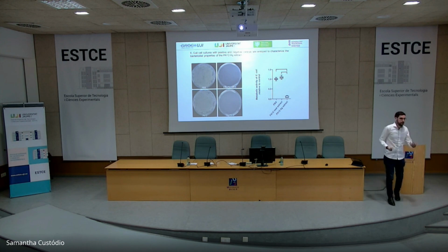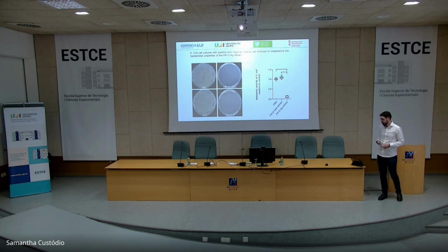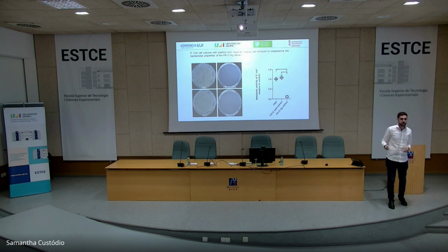So in the case of the base material, where the bacteria can grow, there is no change compared to the base culture media. In the case of the part where we added the silver nanoparticles, we have an inhibition of the growth. Okay, so as I say, it's the beginning, but if we see it a bit more quantitatively, there is basically no difference between the PA12, the base material, and the base media, and then we have almost complete inhibition when we use the PA12 with our silver nanoparticles. I should say that the silver concentration is also pretty low. It's only 0.1 weight percent compared to the base polymer.